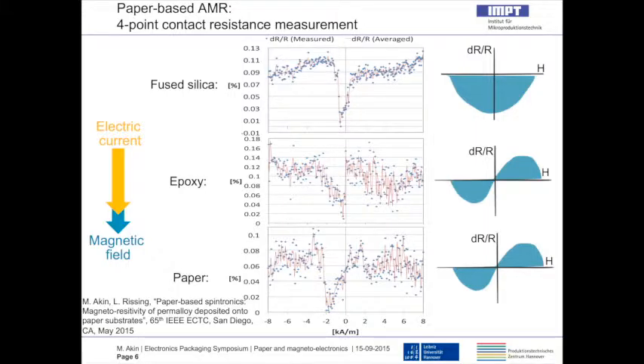So in terms of making magneto-electronics and specifically anisotropic magneto-resistance happen, we first took a piece of paper and deposited an alloy called permalloy, an alloy of nickel and iron, basically two materials where William Thomson discovered the anisotropic magneto-resistance phenomenon. Stepping into his footsteps, we wanted to see what happens on paper when we deposit this soft magnetic material and measure the electrical resistance based on the angle between electric current and magnetic force.